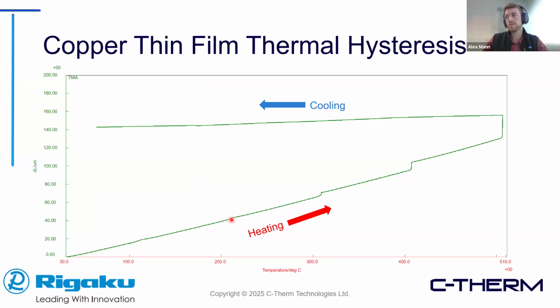At around 200, we see a little bit, but not really that much damage. Around 300 is where we start to see this damage occur. At 400, we see a lot of expansion, and at 500, a lot more expansion. And then this damage done is irreversible.